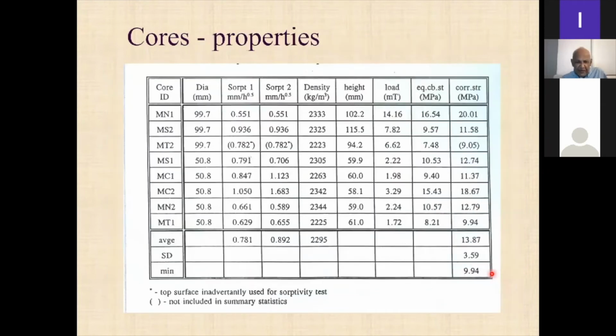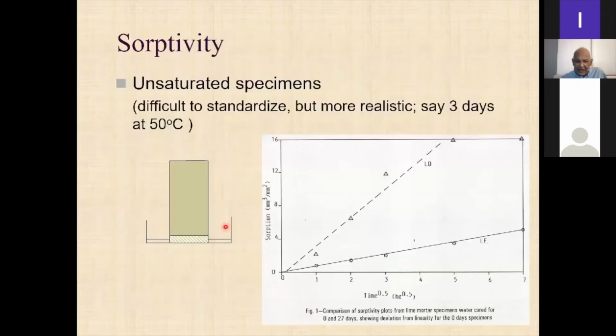Sorptivity, I said if the sorptivity is less than 1 millimeter per square root of hour, then it's generally okay, right? Okay. And this is how you do the sorptivity test. You have a sponge here. You heat this for 50 degrees centigrade for 3 days, and you calculate the amount of water absorbed into that semi-dry specimen, not completely dry, right? But dry to a standardized sort of condition, right?